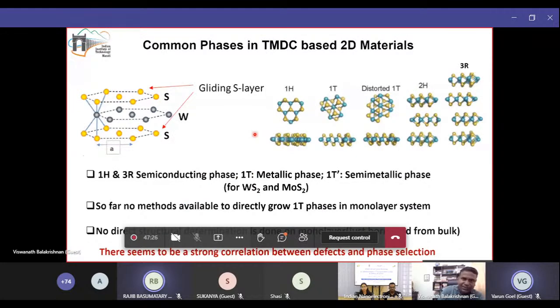What I mean by phases is the allotropic phase, or phase engineering. And just one quick slide. In a 2D material, especially if I take WS2 as an example, as I said earlier, one monolayer essentially has 3 atomic layers. Unlike graphene, which is just one carbon layer with a hexagonal arrangement of carbon atoms, in the case of WS2 we have a tungsten layer sandwiched between 2 sulfur layers. So in most cases during CVD growth, the WS2 forms in what we call the 1H phase.